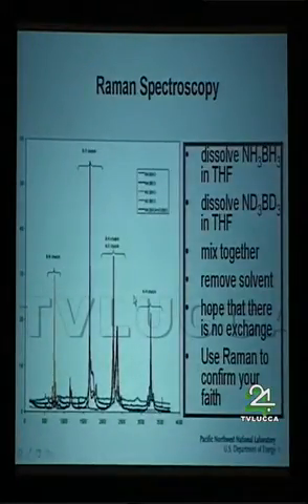So one of the things, the controls that we were concerned about is that there's a report that ammonia borane, it's exchangeable. So if you throw in other amines with this, you can get exchange over a period of time that there was no kinetic studies done. So the one concern we had is that we wanted to make sure we had per deuterated, per proteated, and we did not have the mixed isomer of the species. And so the concept was to dissolve the ammonia borane proteated in one beaker, the per deuterated in another beaker, mix them together and rapidly remove the solvent, and then have a near homogeneous solution. But if there's exchange going on in there, that's going to ruin the experiment, because now if we get HD, it could be coming from the isomer generated in situ in the exchange.